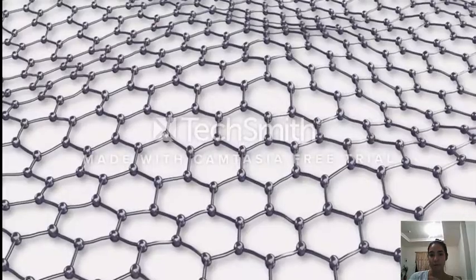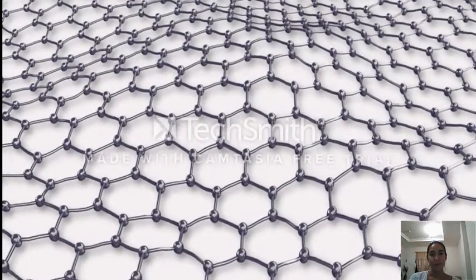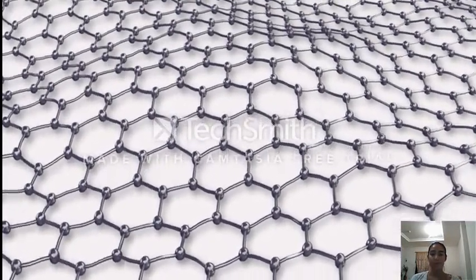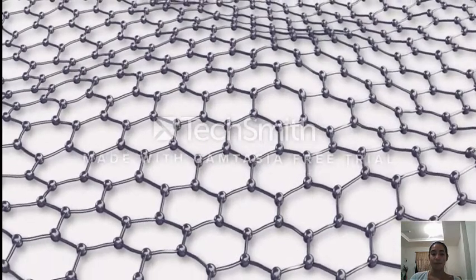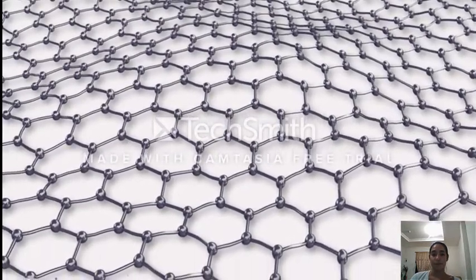So graphene is a single atomic plane of graphite. We've been studying a lot of different properties of graphene. And at one point we decided to make it freestanding. We figured out what was happening is the membrane is kind of shaking around. The atoms are shaking around and vibrating, but then every now and then this local, let's say convex section of the membrane would flip its curvature over and become concave.